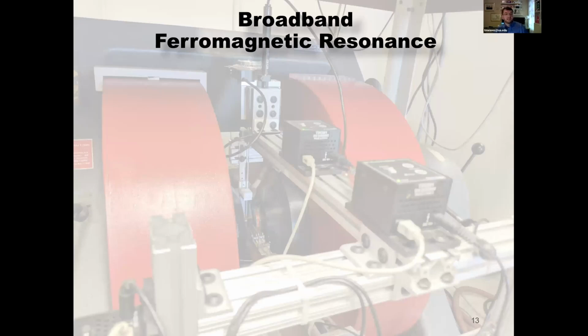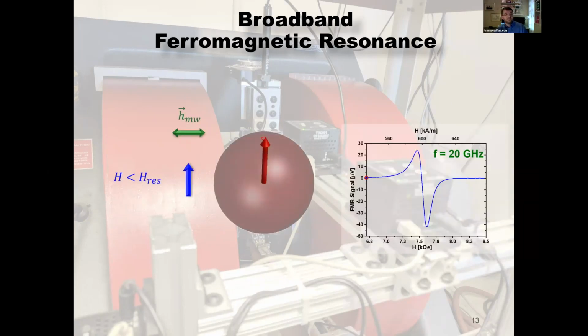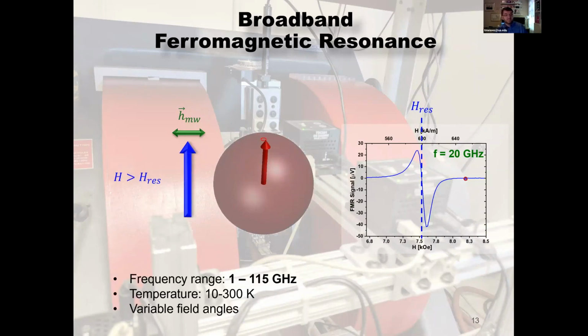Here's another quick animation of how this works. So that's an actual setup. If you drive the system at a given microwave frequency, in this particular case 20 gigahertz, but apply a field that's below the resonance, your precession cone will be very small. But as you increase the field and now hit the resonance condition, you get a large precession cone of your magnetization. Consequently, the system will absorb quite a bit of the microwave power that you supply. And this is actually the resonance of your sample. Obviously, as you increase the field again, you will detune from the resonance condition, and again the precession cone becomes very small.